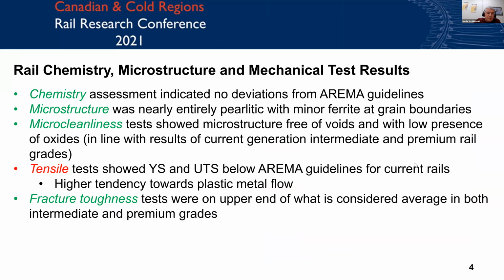So obviously, with this type of investigation, the first step is to look at the obvious things like chemistry, the microstructure, and the mechanical properties of the rail itself to find out if there's any smoking gun in those types of things. So we looked at the chemistry, and the assessment showed that there were no deviations between that specific rail grade and the AREMA grade for standard rails.